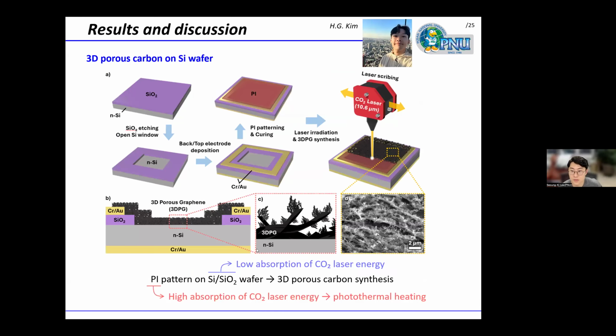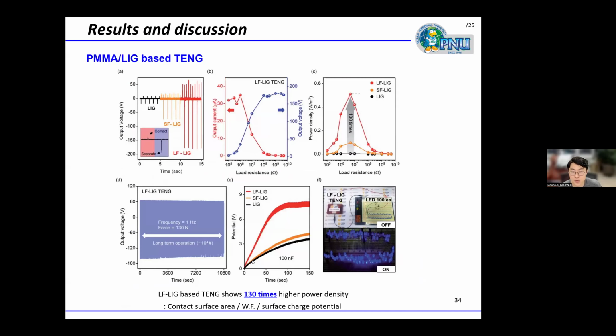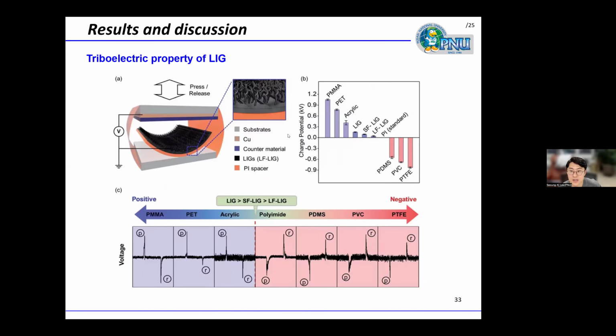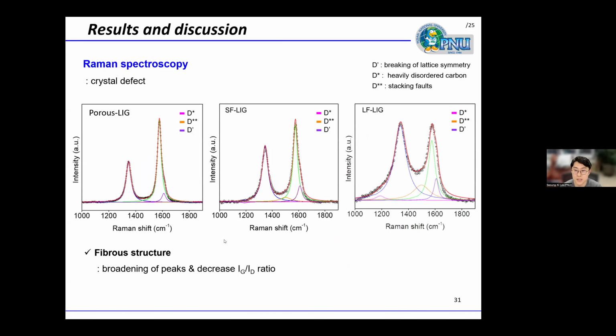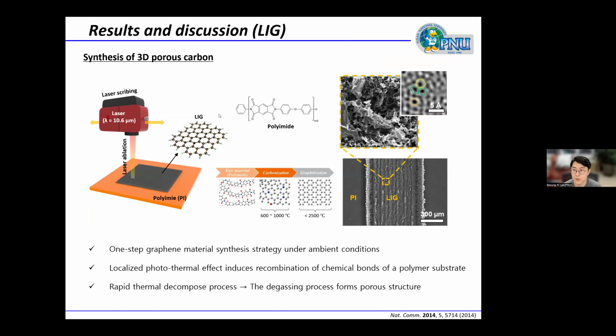Generally, it depends on what kind of polyimide is used in this system. When we synthesize LIG on this kind of polyimide system, in the porous LIG system the surface area is around 400 or 500. I'm not sure, but Professor Spiros, do you know the exact surface area of LIG? Yeah, I think in the literature it is between 150 and 500, depending on the way you produce it. Yes, but it's typically a few hundred square meters per gram. It depends on the structure of the LIG, so it has a broad range of surface area.